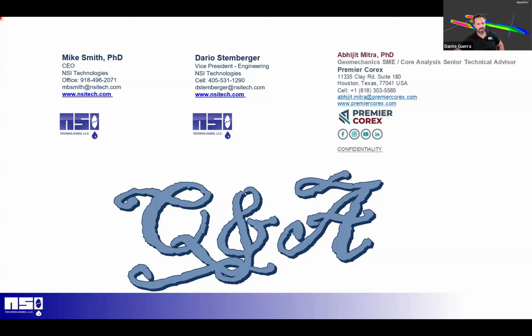To ensure that when we're injecting into saltwater or wastewater disposal wells, we're not exceeding the fracture gradient. But in the event, I believe the question here is if we could execute a controlled hydraulic fracture where we know we can contain the frac height in the injection zone, we increase the surface area, we have proppant there. So in effect, we're increasing the injectivity for that well and making it a significantly better injector. Is this something that is commonly applied or something that we recommended? And I open the question to Mike, Dario.